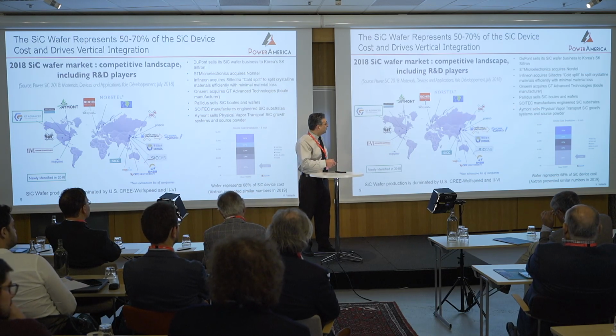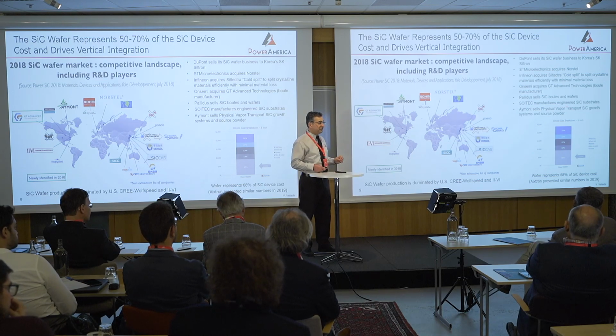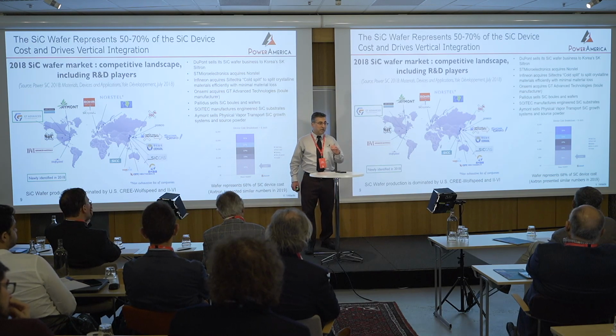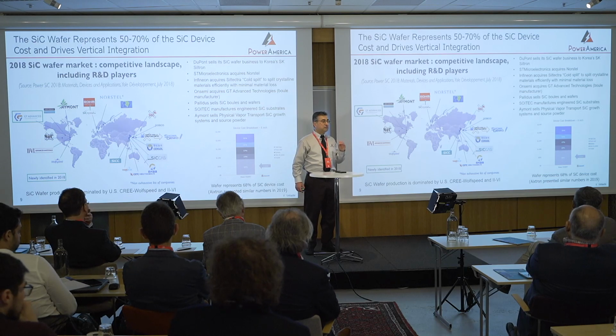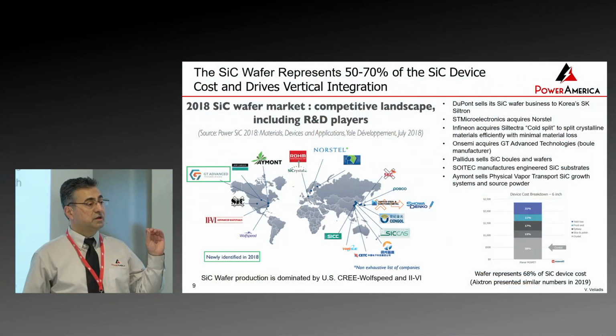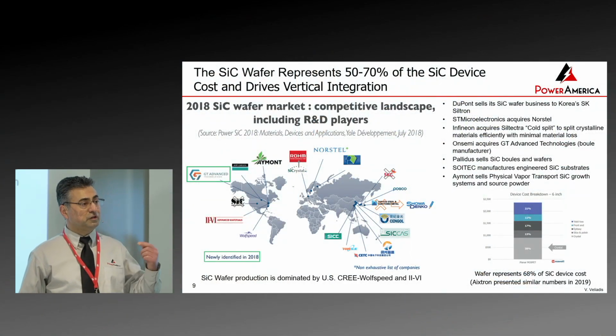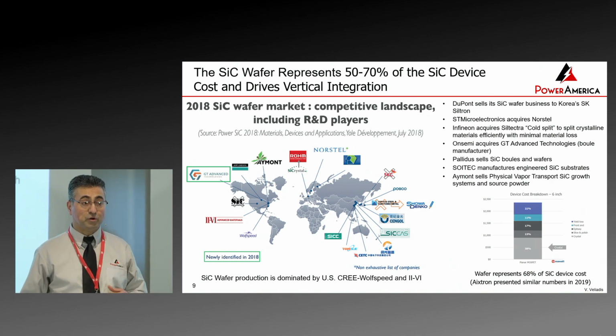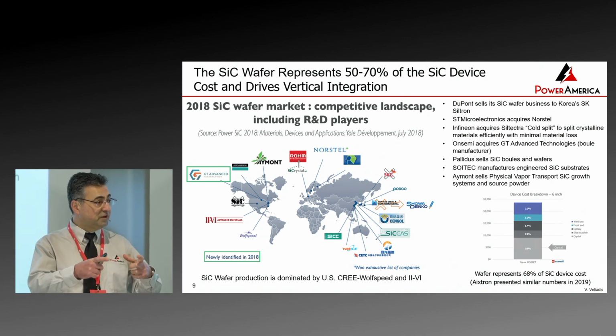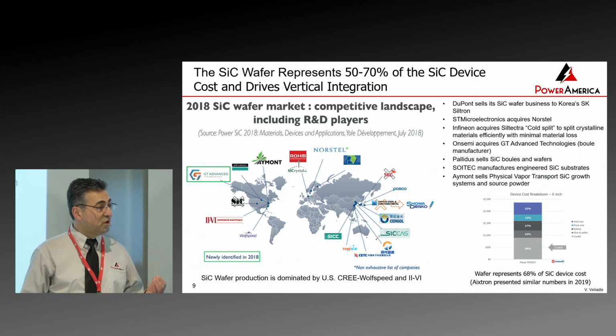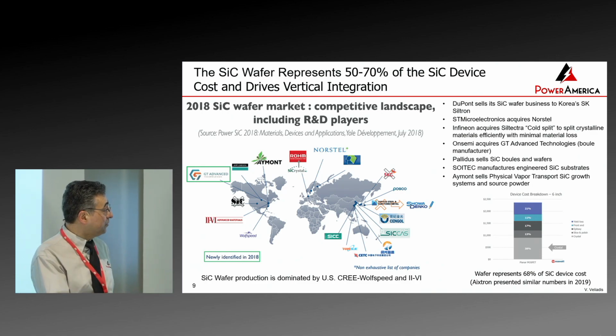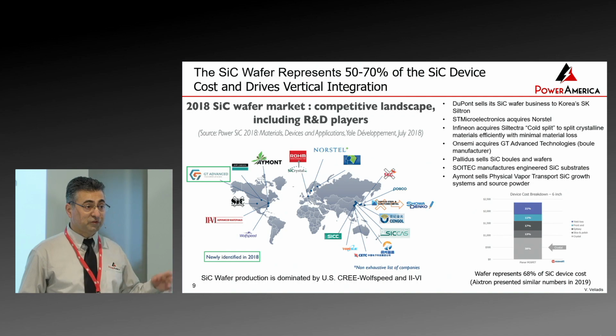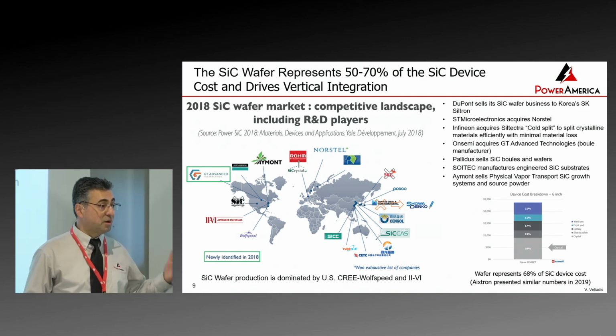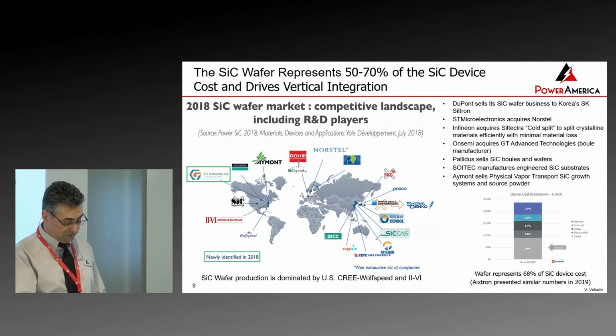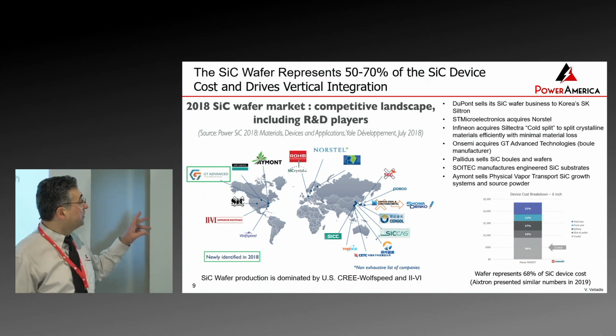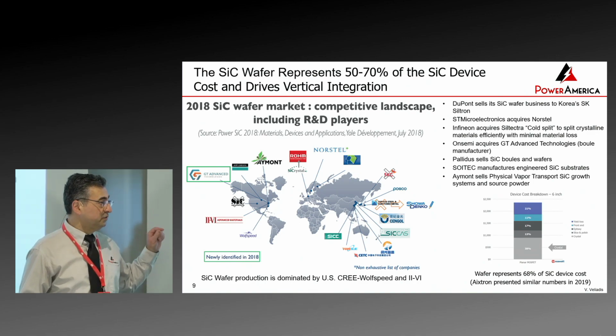And also take into consideration that anytime there is a very difficult way of making anything, there are going to be disruptive technologies. Well, how about if there's a way to get silicon carbide substrates where you don't need to go to 2,500 degrees, where you don't need a nice, large, clean seed, and you can make a wafer at much lower cost? So engineered substrates are a very big business. Soitec has announced some products, and there are other companies out there that are working in that technology. So moving forward, the substrate will remain key.